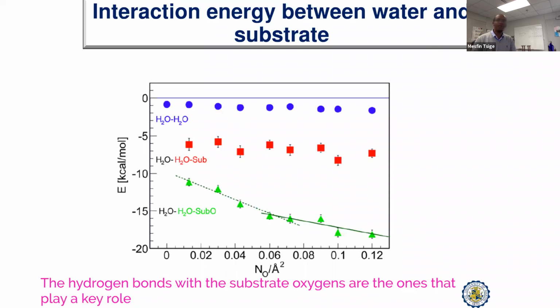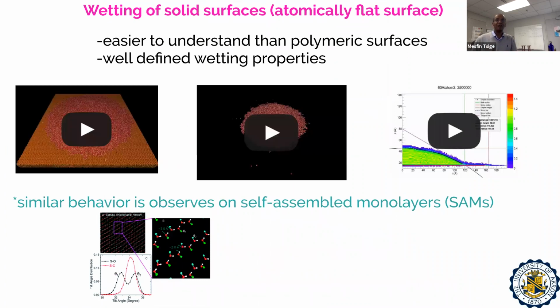I know I'm getting closer to my time, but I would also like to tell you what we have done for the case of atomically flat surfaces. That means surfaces that don't have roughness, highly oxidized, which show complete wetting. When we look at complete wetting, the wetting property is completely different. In this particular case, we considered sapphire, the alpha form of aluminum oxide. It is used as a catalyst and catalyst support, and in some cases in microelectronic devices. So its interaction with water is very important.